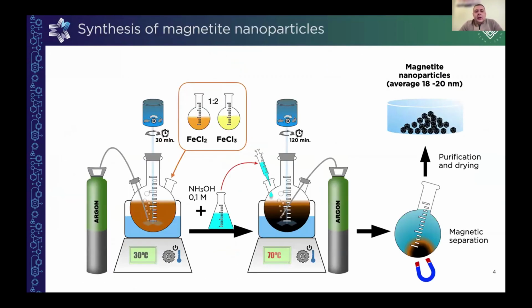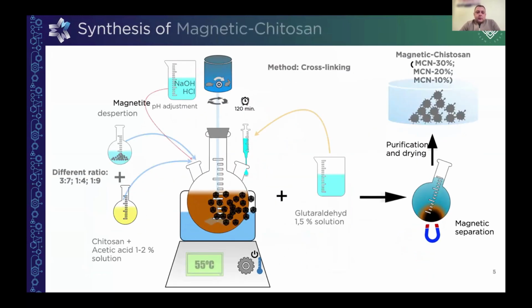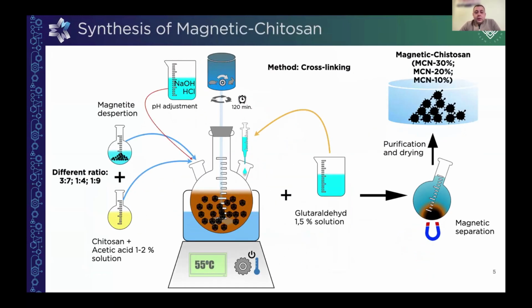So first of all, we synthesized the magnetite by dissolving divalent and trivalent iron chlorides, and then with the addition of ammonia, the reaction was launched, and the magnetite nanoparticles were grown during about 2 hours of synthesis. After that they were purified, dried and homogenized for better dosage and to ensure that we can correctly set the ratio of magnetite to chitosan. It's 10, 20, and 30%.